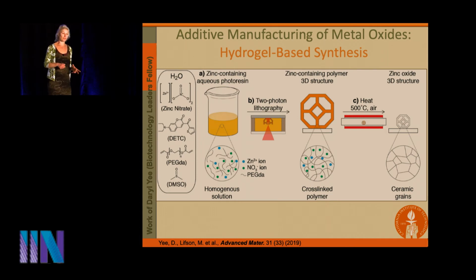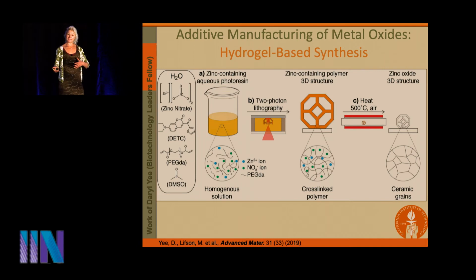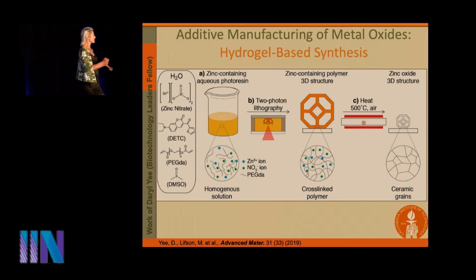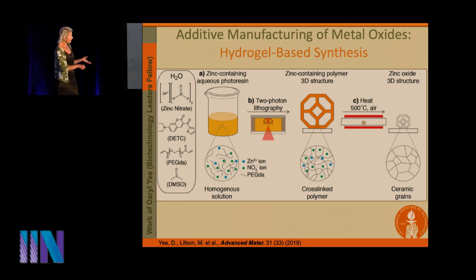So now what Daryl noticed is that if you take a metal salt, and in this particular example, he's using zinc nitrate, you can use this metal salt based synthesis to do a swell-in type of reaction, and then cross-linking and trapping the metal ions inside of this hydrogel network. And then it's no longer called pyrolysis. So when you burn things with oxygen, it's called calcination. I'm learning all sorts of chemical things here. So when you calcinate this in air, what we end up with in this particular case is a zinc oxide architecture using aqueous only synthesis, no acrylates here.